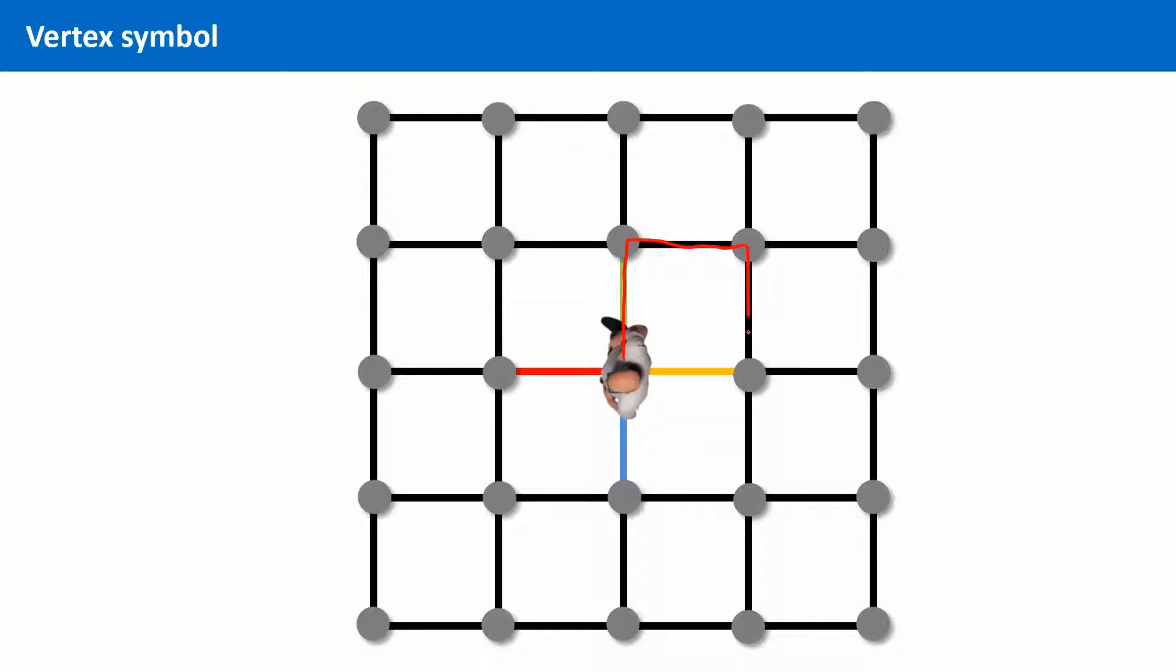As you are already very familiar with symmetry operations, you probably see immediately that all four combinations of edges that form an angle on this vertex have the same ring size. We write this down as 4 times 4 times 4 times 4, or as 4 to the power of 4. This is called a vertex symbol.